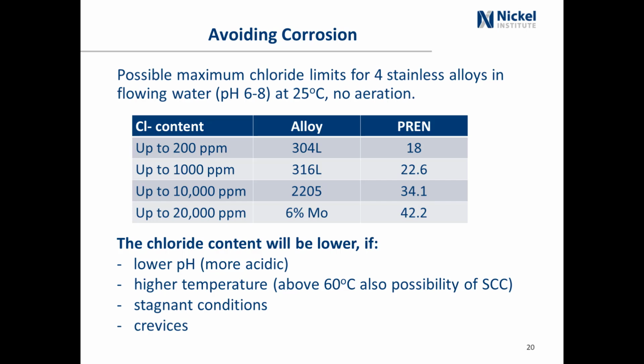And 304L, we would generally say, okay, it's going to be good in about 200 parts per million chloride. 316 in about 1,000 parts per million chloride. 2205, 10,000 parts per million chloride. And 6 moly up to about 20,000 parts per million chloride. And 6 moly stainless steels, because of this resistance to chloride, they're considered seawater resistant. So they have a really good resistance.